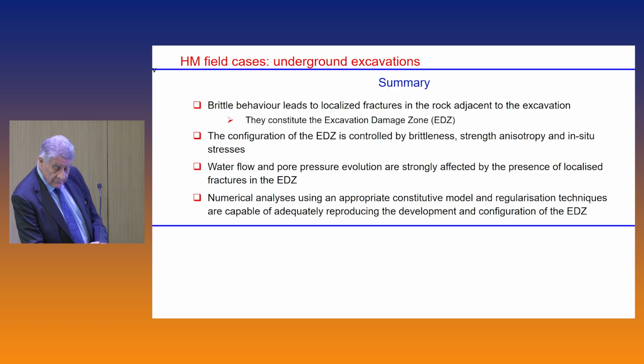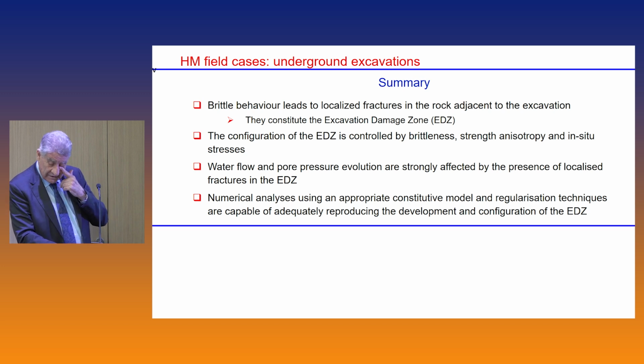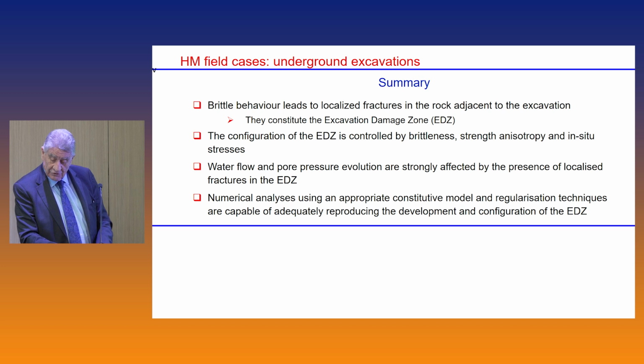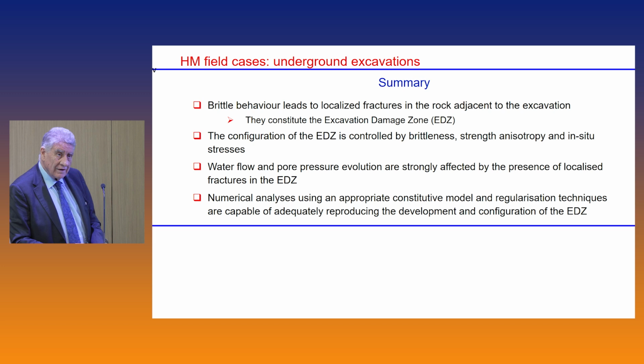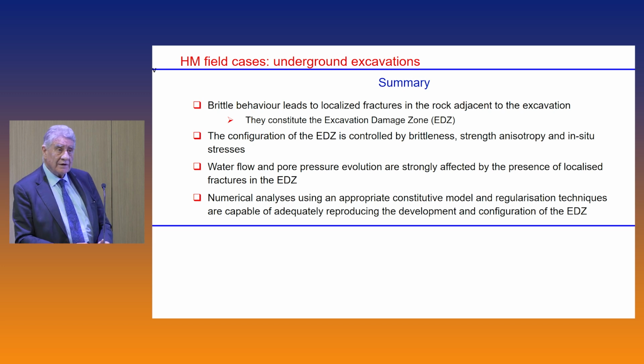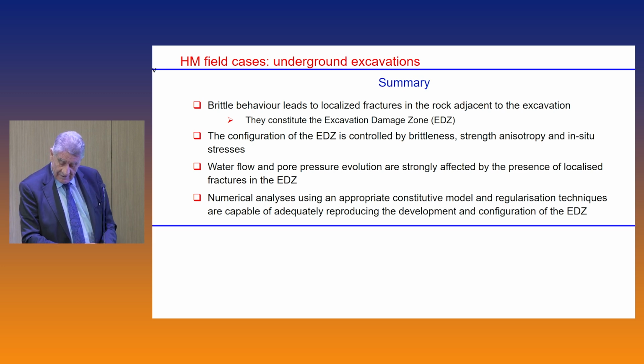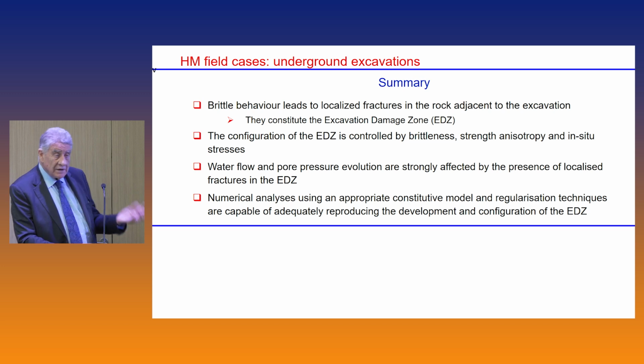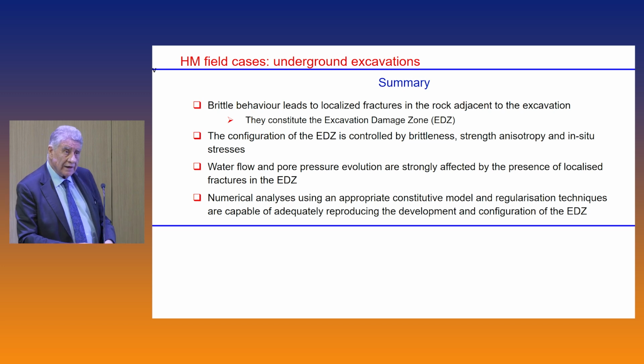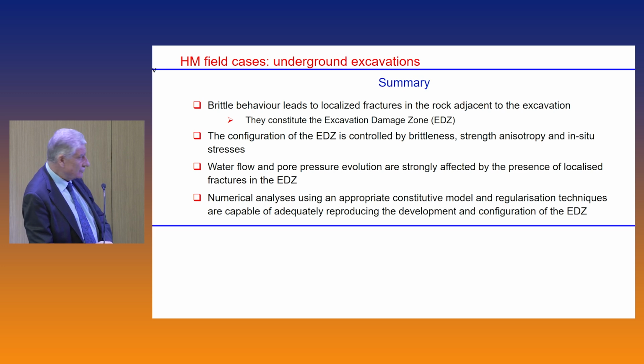So I can now summarize this bit. Brittle behavior leads to localized fractures in the rock adjacent to the excavation, which are a component of the EDZ, and that configuration is controlled by brittleness, strength anisotropy, and in situ stresses. The importance of each one is different depending on the orientation. The water flow and pore pressure evolution are strongly affected, as we have seen, by the presence of these localized zones, and it seems that with the formulation used, we get a reasonable representation using this numerical model.